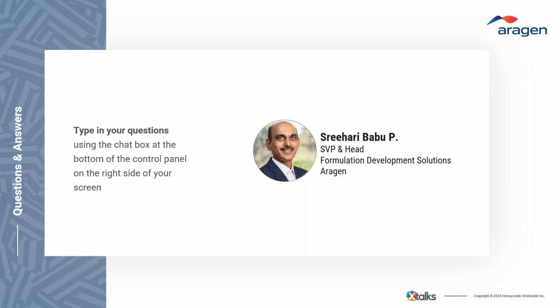So Sreehari, the first question here is, what is the typical timeline of ASD development? Typical screening takes around 4 to 6 weeks, followed by process development for another 2 to 4 weeks. So it typically takes about 8 weeks to complete screening to process development. And then there will be an additional 6 to 8 months to develop and convert into a clinical formulation like a tablet dosage form.